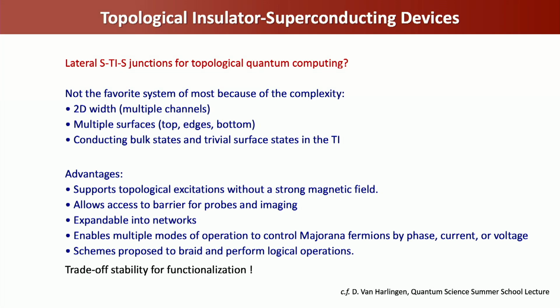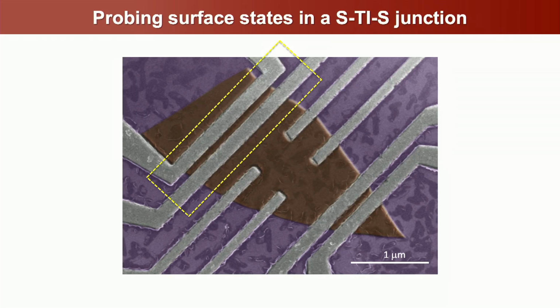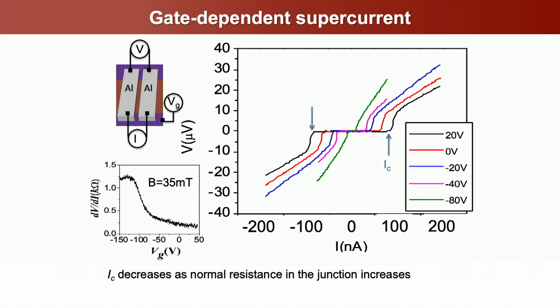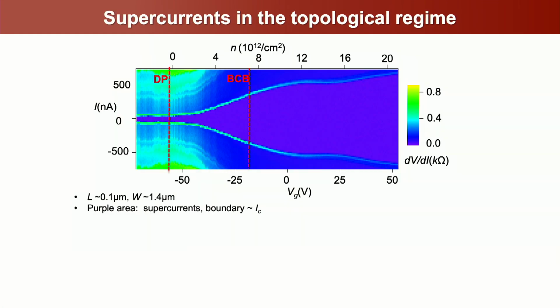So the other thing that we've done is looked at surface states. So you might ask, if you have a topological system, what do the superconducting surface states look like? And here we have another flake, the same picture, but a flake that looks like this with aluminum leads on it that make a very narrow junction to see if there are unique surface state properties in the superconducting regime. In this case, you can see clear gate tunable supercurrents, which is expected for these sort of systems, but you can couple it very well. Again, we can tune the supercurrents through the Dirac point and see how they behave, and whether you get differences in the supercurrent near the Dirac point, as opposed to around the bottom of the bulk conduction band.